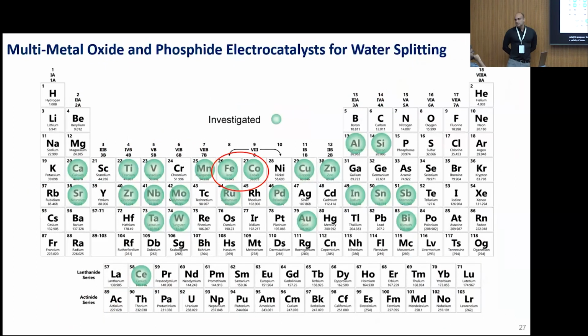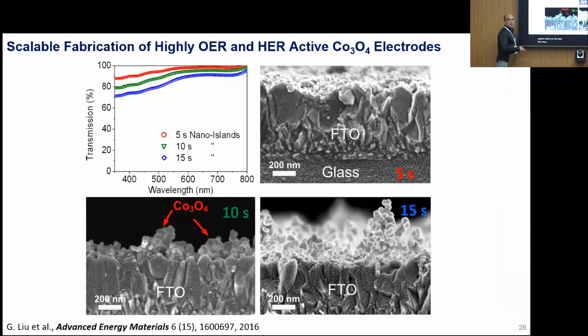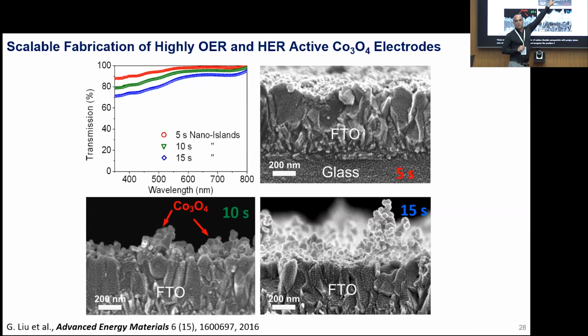In the past 10 years, we have been investigating all these materials by flame synthesis, trying to combine them, trying to find the best electrocatalysts. And there are too many possibilities to show you all of them. I'm going to show you two of the best ones, in my opinion, which are cobalt-based and iron-based. Also, they're cheap. This is an example of a very thin layer of cobalt oxide nanoparticles with a very high surface area. We are above 100 square meter per gram, deposited in 5 seconds only on a conductive substrate. And then we can increase the time.